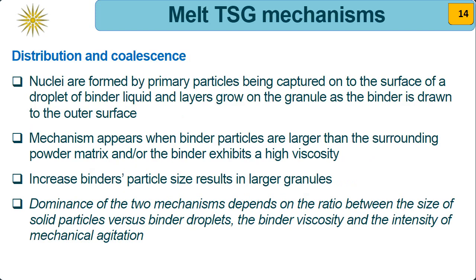The second mechanism is known as distribution and coalescence, and the nuclei are formed by primary particles being captured onto the surface of the droplet of the binder, and they later start growing around the granule as the binder is drawn to the outer surface. The mechanism appears when the binder particles are large, usually larger than the surrounding powder matrix, and the binder exhibits high viscosity. The increased binder particle size results in larger granules, and eventually it was concluded that the dominance of the two different mechanisms depends on the ratio between the size of the solid particles versus the binder droplets, the binder viscosity, and the intensity of the mechanical agitation.